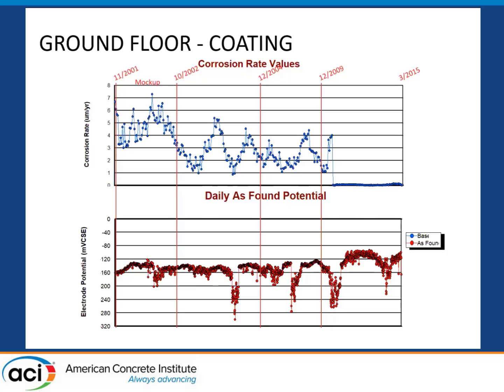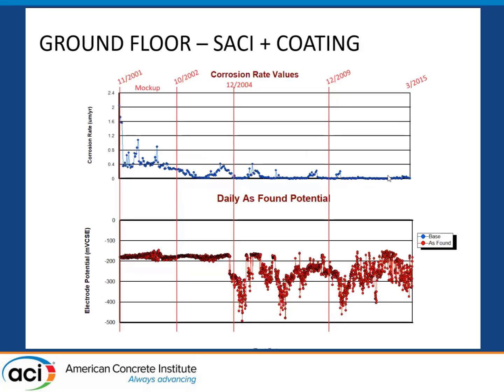And if we go back to our mock-ups for that 10-year period, here's the one with just the coating. You can see that at least for the first 5-6 years, it did seem to struggle to maintain those corrosion rates. But somewhere around year 6 or so, it eventually got to passive. And then the surface applied corrosion inhibitor plus the coating, again, was very consistent throughout. When the project was finished, and through the monitoring over the 10 years, it got down to passive and stayed consistently down there with very little variation in corrosion rates.